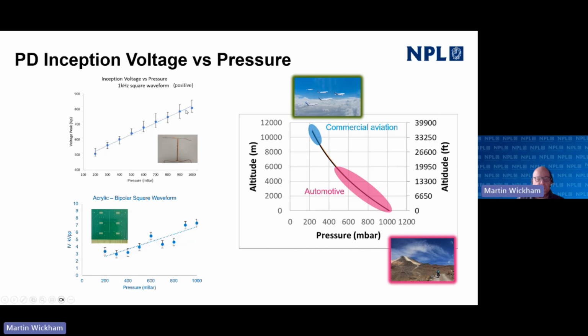This is a twisted wire pair. This is an acrylic conformal coating on the surface, and you can see, if we look at this acrylic coating, because this is the sort of thing we'll come back to in a bit more depth in a moment, you can see that at ambient pressure, 1000 millibar, we're up around 6-7 kV, and when we get down to 200 millibar in this case, it's around 3.5. So we've seen a 50% reduction in the inception voltage at which this PD occurs as we go to low pressure. And these pressures of 200 millibar are typically the sorts of pressures at commercial aviation heights. So they're talking about sort of 10,000 meters, 30,000+ feet.